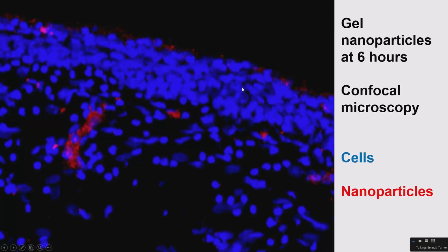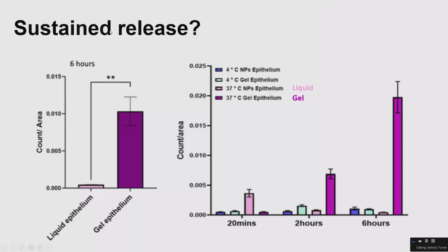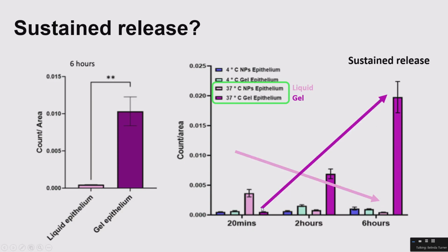And this is just a nice image, a confocal image of the gel nanoparticles at 6 hours of treatment in red, and the cells are in blue. So she did show that the gel formulation versus the liquid did show sustained release. So you can see in the pink here, the liquid formulation peaks at 20 minutes and decreases at 6 hours, and the gel is the opposite. It peaks at 6 hours versus the 20 minutes.